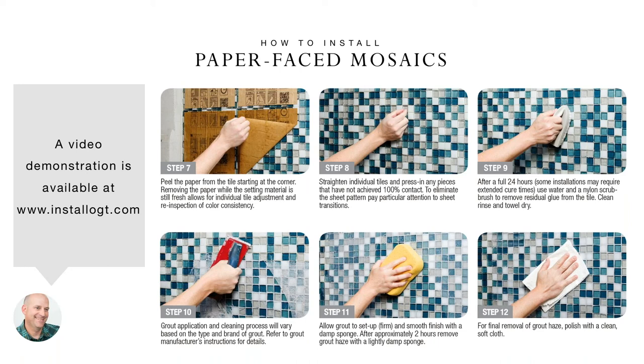And then you're gonna let this installation cure for 24 hours. This is not tile setter 24 hours where you finish work at 4 in the afternoon and come back at 7 and start cleaning. Since glass is impervious and we're using highly modified thin sets, we need to let the thin set cure for a little bit longer.